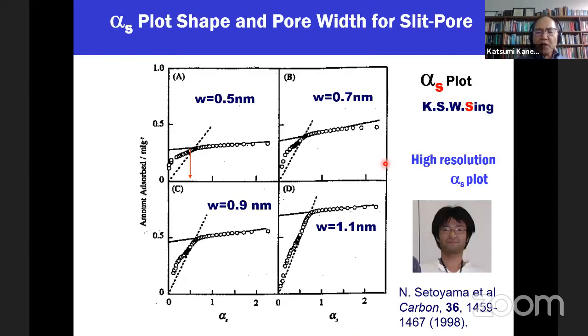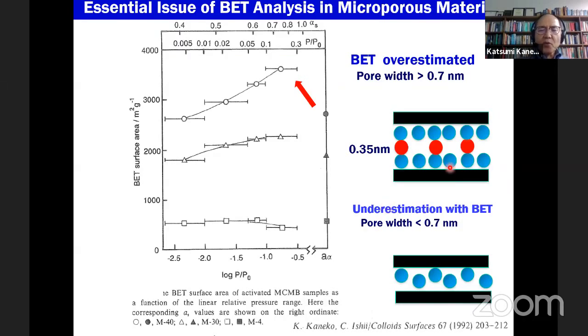Then we apply the high resolution alpha S plot. I already mentioned that Kenneth Sing applied this alpha S plot. This S comes from Sing. In our case, we measure the adsorption isotherm from 10 to the minus 6 relative pressure. Then we plotted this kind of alpha S plot. In the 0.7 nanometer case, almost the exact surface area is obtained, and for 1.1 nanometer also almost okay. The slope gives the correct surface area, in agreement with experiments and simulations.